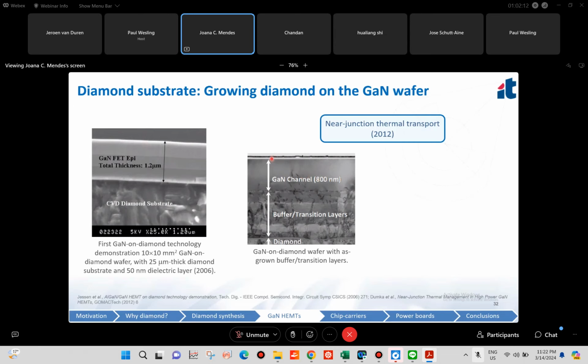But then between the channel and the diamond, we have all the aluminum nitride nucleation layers, all the strain relief layers and transition layers, and we also have the GaN buffer. This is required because we grow GaN on a 4-inch substrate, so we have to match the lattice mismatch, the lattice parameters. So we have a very large thermal resistance from the hotspot to the back of the